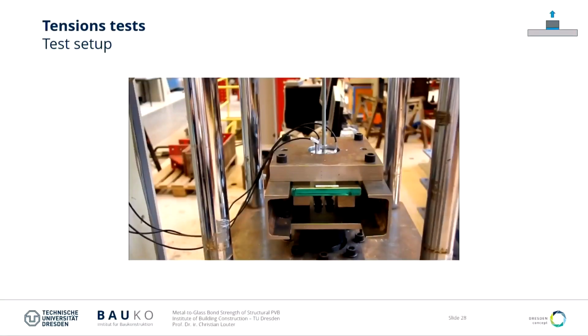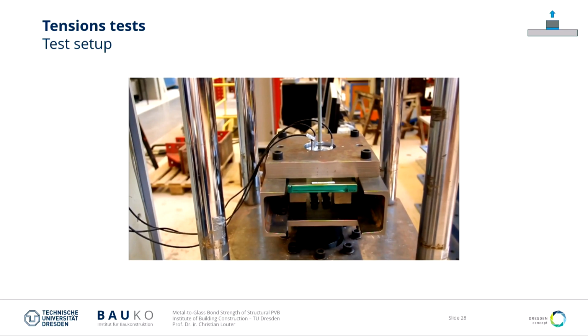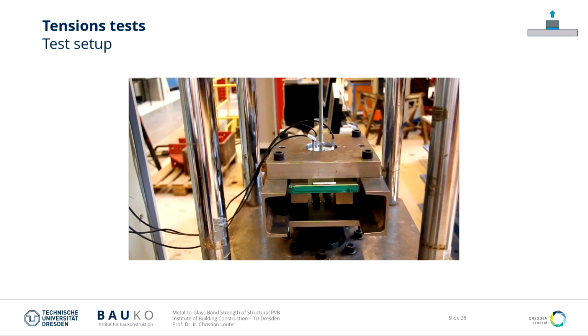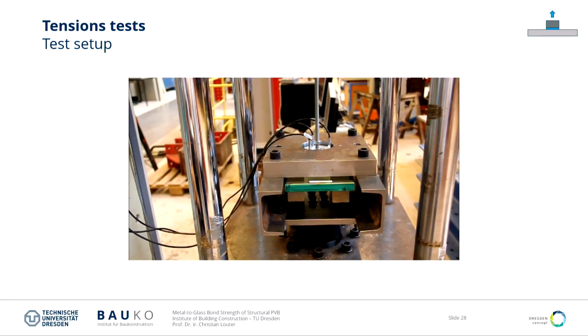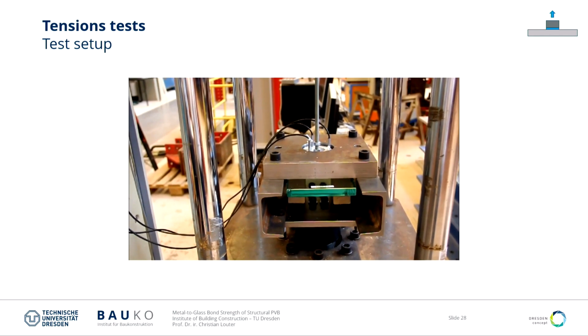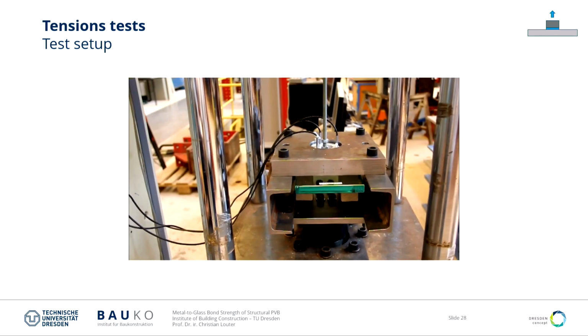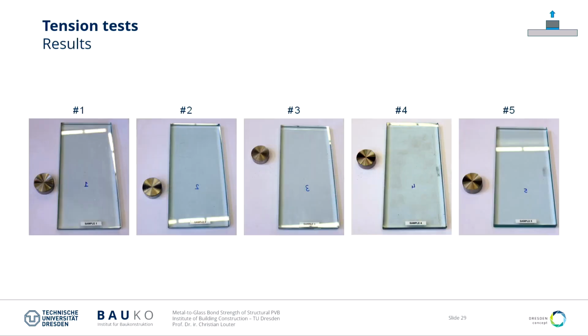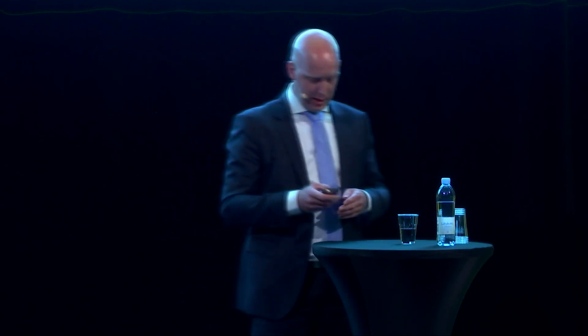This is the test setup, just a short video. You don't see that much happening. There's also no sound, but at the end you see that the piece comes down from the metal button there. Again, for the 5 specimens that we have tested, you can see delamination for all the specimens at the failure load.